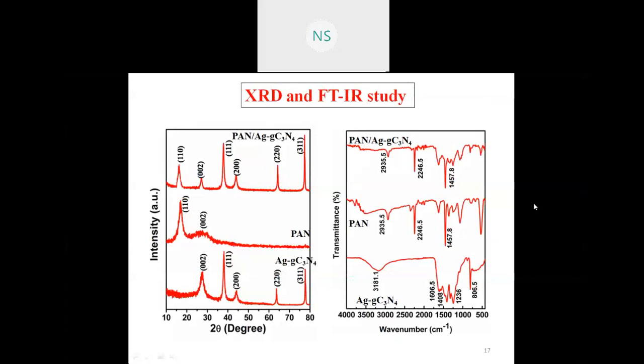This is the characterization we have done for that material. We did XRD, with three patterns: the nanofiber, pure polyacrylonitrile, and pure silver grafted carbon nitride nanomaterial. The observed peaks are the crystal planes. The combination of all these peaks is seen in the first peak of the XRD for the nanofiber, which suggests that a combination has happened for PAN, Ag-g-C3N4.